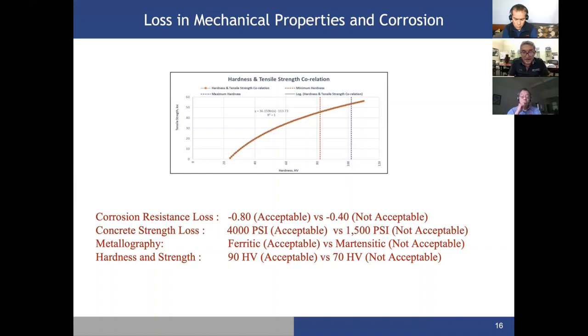Hardness and strength also provide a very good performance indicator from a mechanical properties point of view. A 90 hardness measurement, Vickers hardness, is acceptable versus a 70 hardness, Vickers hardness measurement is not acceptable. So you can see we have quantified the risk and have critical values for acceptance or non-acceptance.